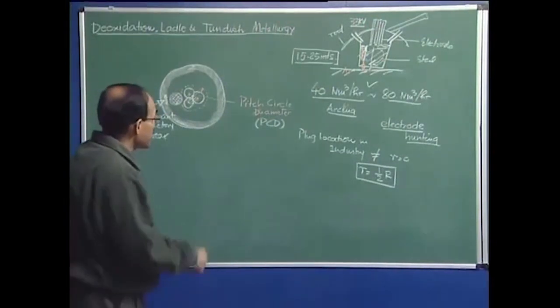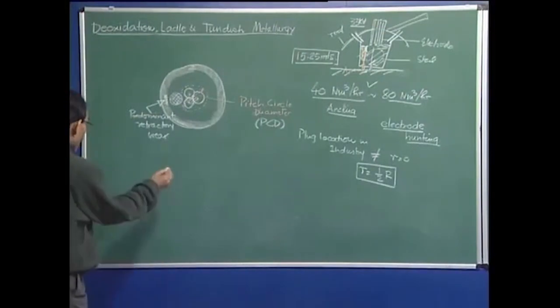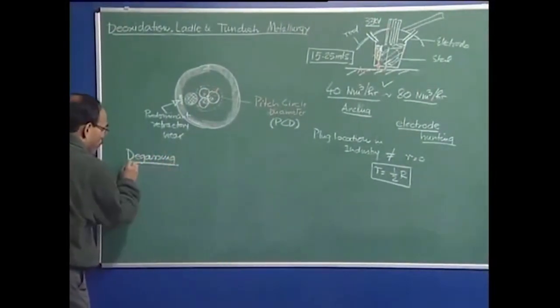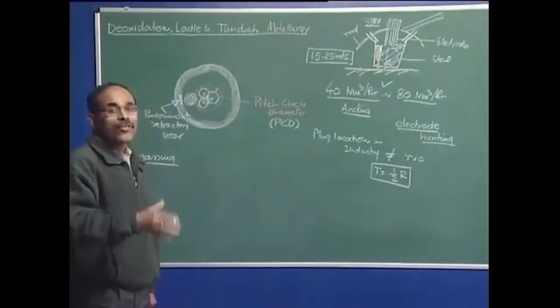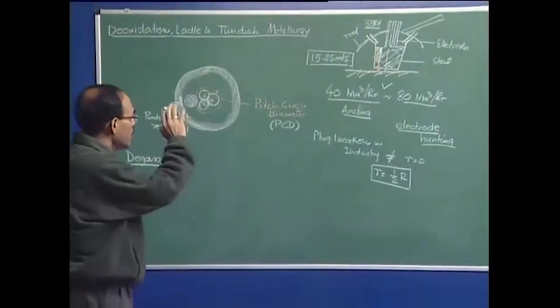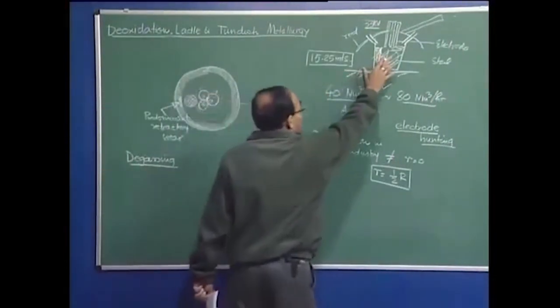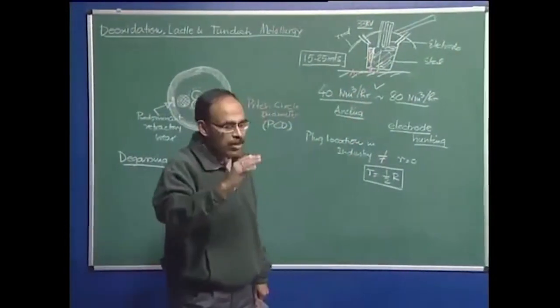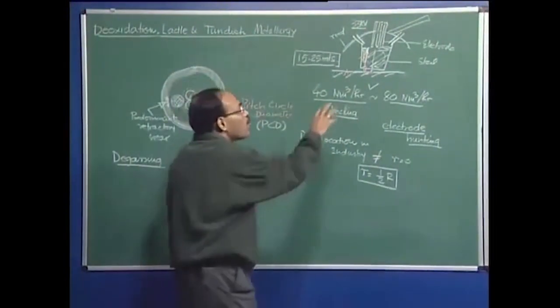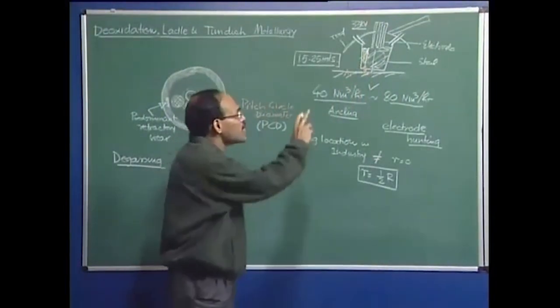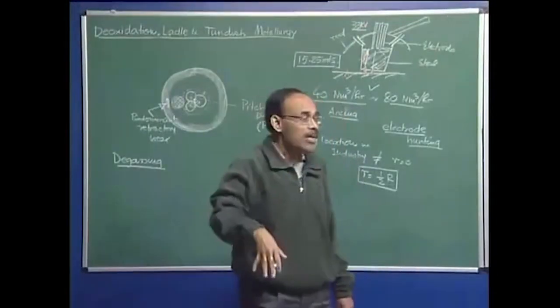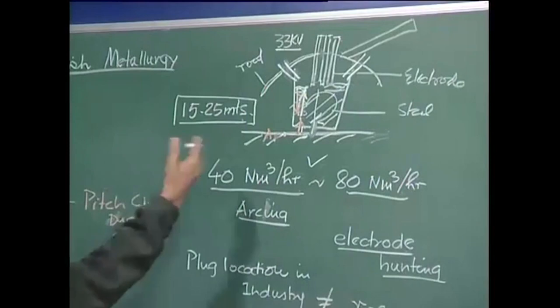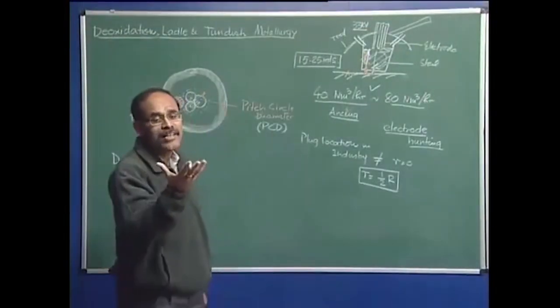Having said this, let us move to the next section of ladle metallurgy — degassing. The temperature drops during tapping, holding, and melting/dissolution are compensated through the ladle furnace. When the material leaves the ladle furnace, it has slightly more temperature than desired, and its composition is correct in terms of solutes, but it may still contain nitrogen — absorbed during furnace tapping — and hydrogen, which may have been absorbed from hygroscopic materials such as the lime added to make the slag.